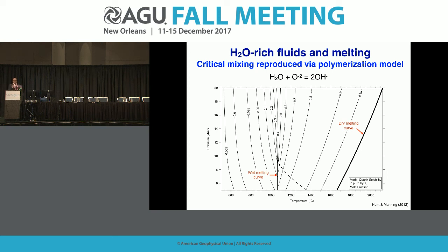This was, of course, interesting in that context for the speciation of water, but in this context it is interesting for the way in which the O2 minus, the bridging oxygens in the silicate melt, are formed or broken. And using the thermodynamics for SiO2-H2O, a thermodynamic model that we built here, we can predict the phase diagram for H2O-SiO2.